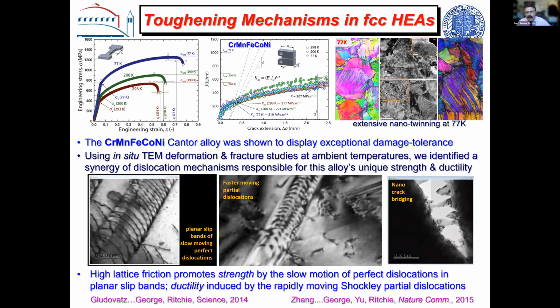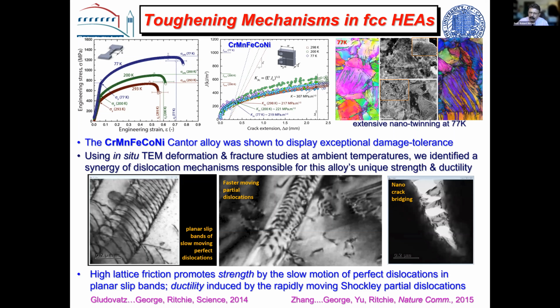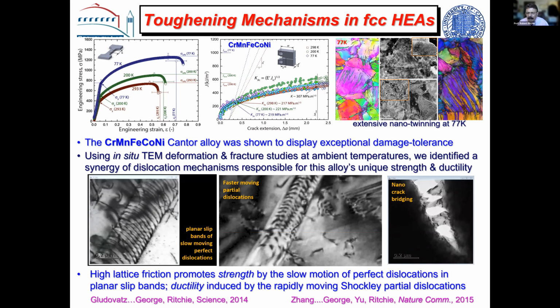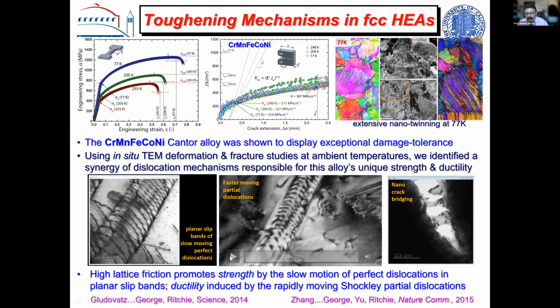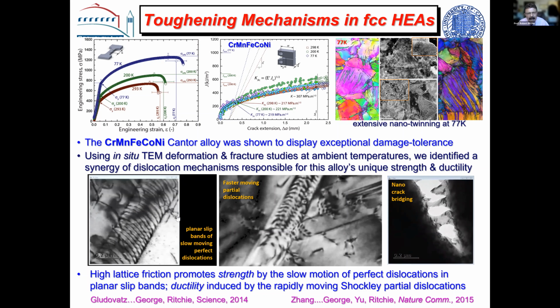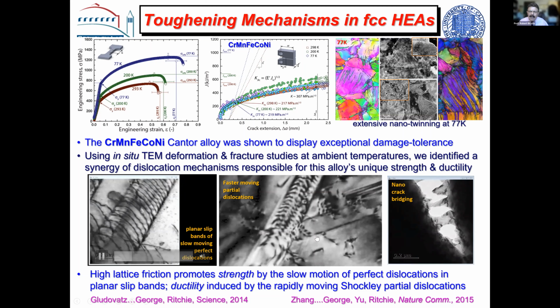But when we looked at them in the microscope, we saw the duality of deformation mechanisms, which speaks to the ductility and the strength. They're not in conflict here. So if you look at, for example, this is a planar slip band in this alloy, and you see perfect dislocations are moving along that slip band in a rather slow fashion, presumably because of the high lattice friction. But if we look at a somewhat higher strain, you'll see the same slip band, but look what comes in here. See that fast? That was a partial dislocation, which can move very, very rapidly. So we have mechanisms here, ponderous mechanisms, which give us strength, and these rapid motion of the partials that can give us some degree of ductility.